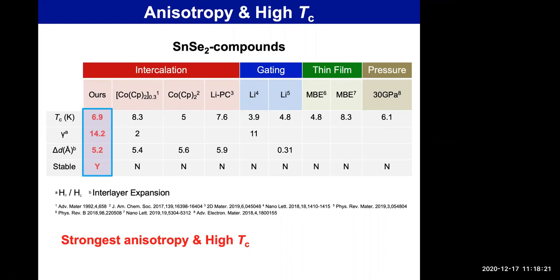The reason I ask is because there has been a lot of work in the past 40 years on other superconductors, mainly on layered superconductors such as copper oxides, where people were puzzled and are still puzzled on the TC dependence on the interlayer spacing or on the C-axis interlayer interaction. In fact, there was this good material, mercury barium calcium copper oxide, where people could insert up to 5 layers of copper oxide. As the number of layers of copper oxide increases, TC increases up to 150 or 160 Kelvin. But there is a maximum.